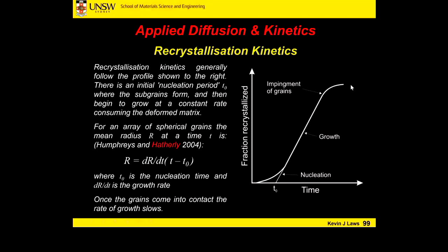This is because the grains start to impinge on each other. Growing recrystallized grains will start to touch each other, and basically the two energies of those defect-free grains are equal, right? So they don't take over one another too much. The rest of this process is just filling in the spots where the grains haven't touched yet.